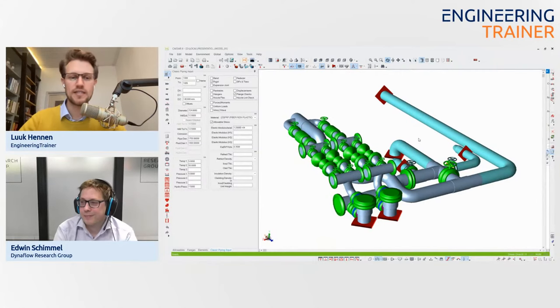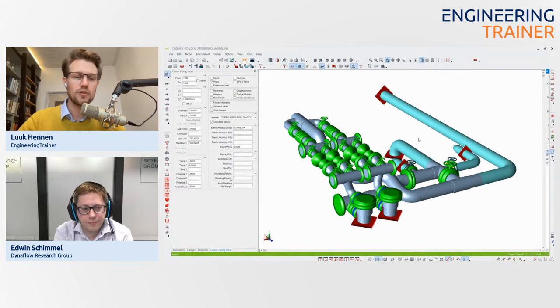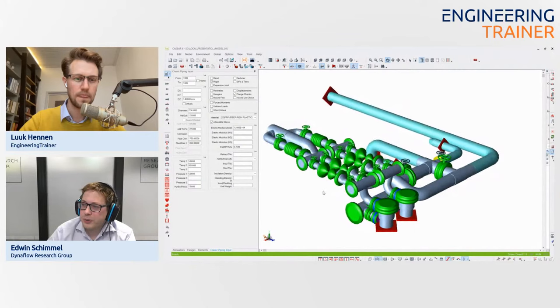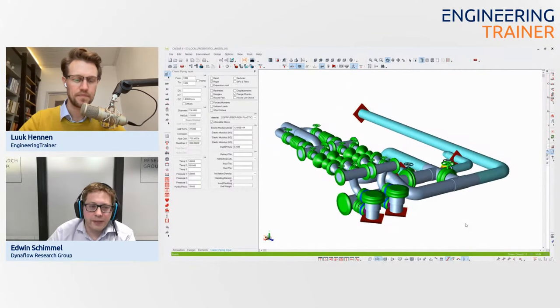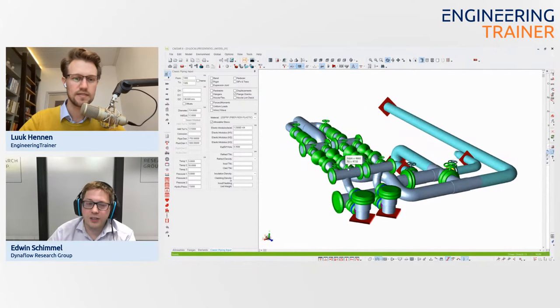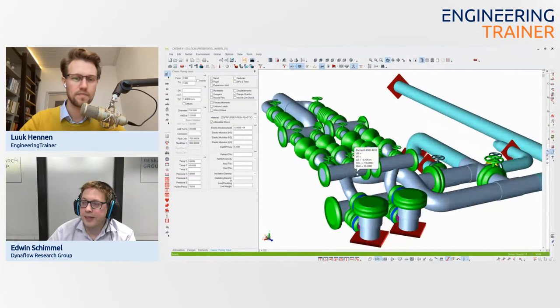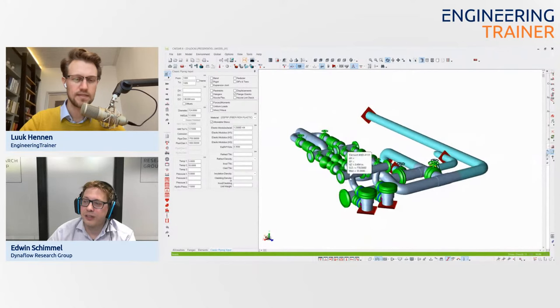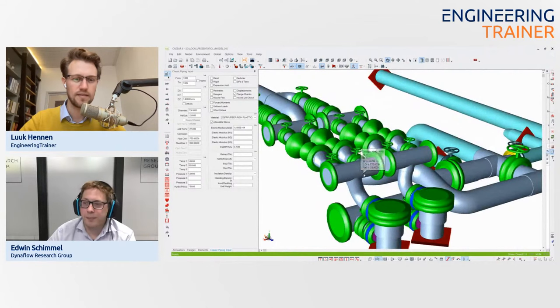So just looking at this system, it's a very compact system, as you mentioned. So what are typical solution methods that you can apply when working with fiberglass if you obtain any high stresses during analysis? Yeah. When you analyze carbon steel piping, what you most often see is that the fitting is overstressed, for example the T, because it has a high stress concentration due to the discontinuity. And with fiberglass, you see that less often because the fiberglass fittings are made significantly thicker compared to the straight pipe. Typically the total wall thickness of the T is twice that of the connecting pipe of the same size. So due to this, the fittings are normally not the weakest point, like in steel.